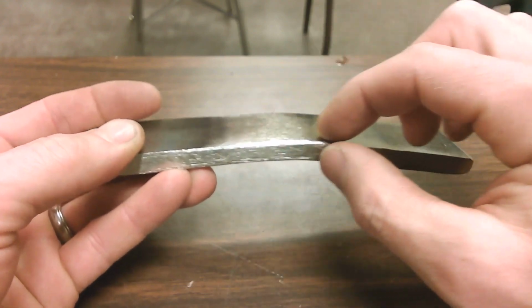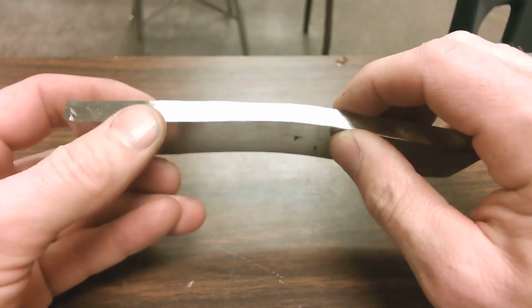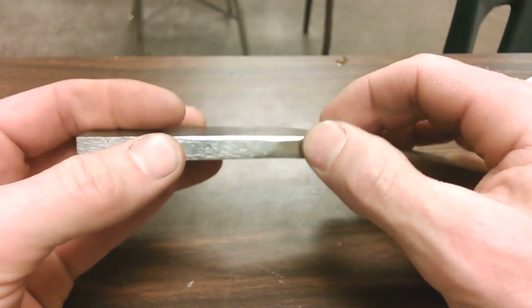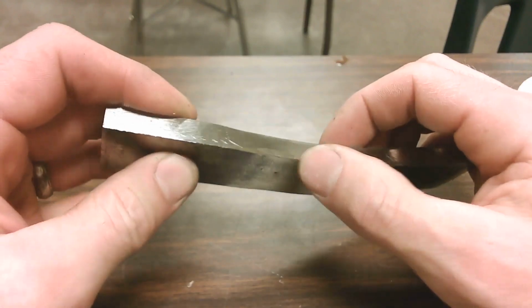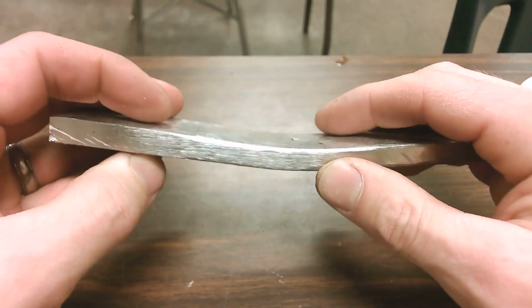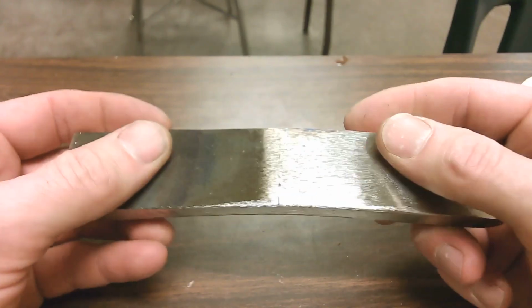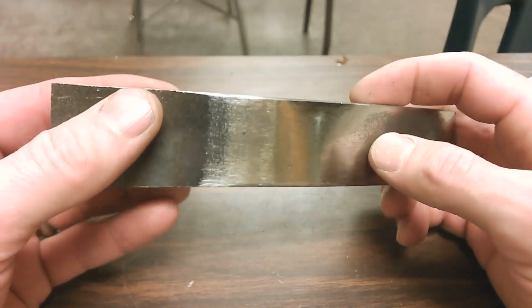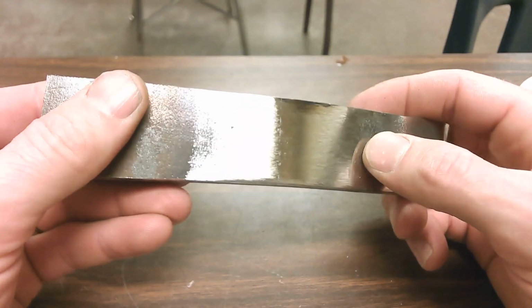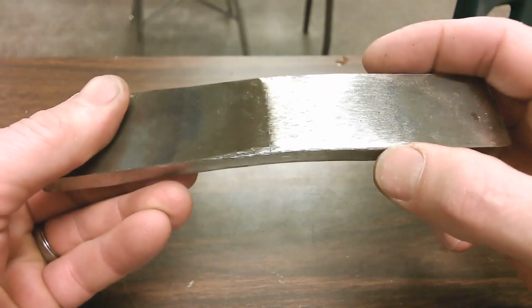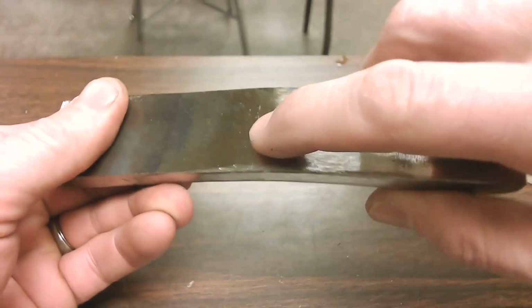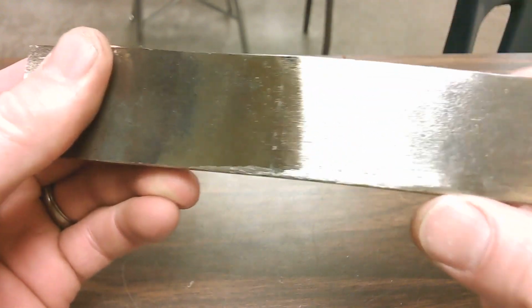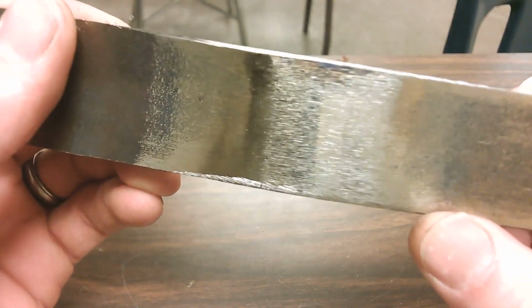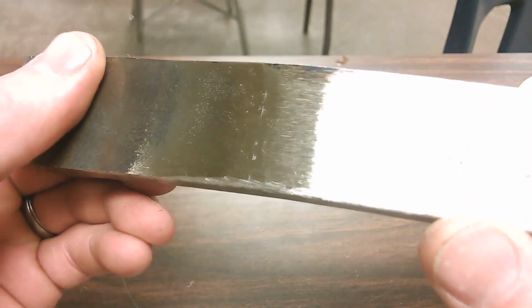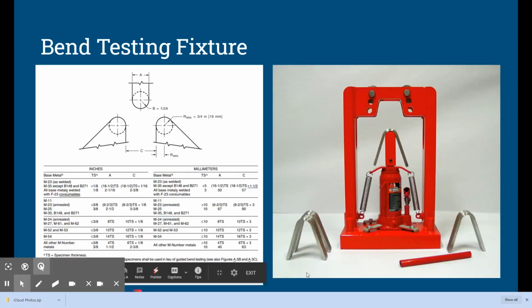Also, the area where it bends, I rolled the edges so we have a slight radius there. We want to make sure there's a slight radius that helps the bend. You're allowed 1/8 of an inch. Okay. All right, so if we flip it over, you can see on the back right away, there's an area of concern. Right there, there's a faint little line. And you can see some areas where it just didn't quite fuse.